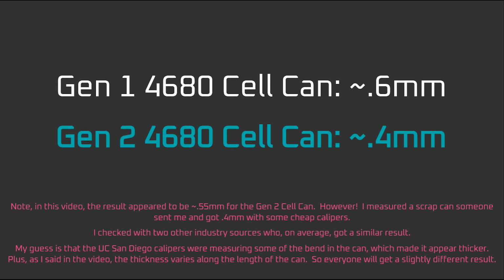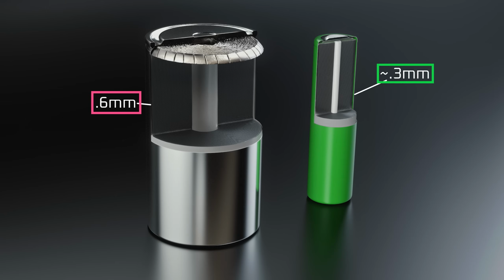The Generation 2 4680 cell, as I showed in the 4680 teardown video last month, was around 0.4 millimeters thick as compared to the 0.6 millimeters thick of the Generation 1 4680 cell can, which was a reduction in thickness of 0.2 millimeters. That is, only about 2/3 of the 0.3 millimeters I was hoping for.